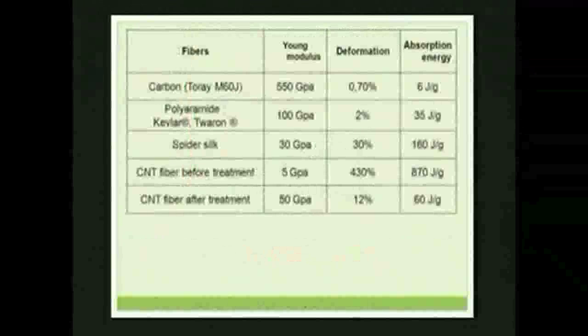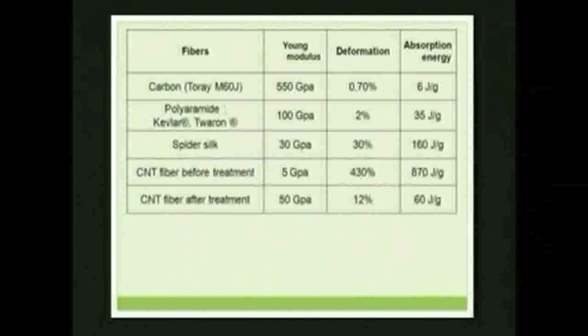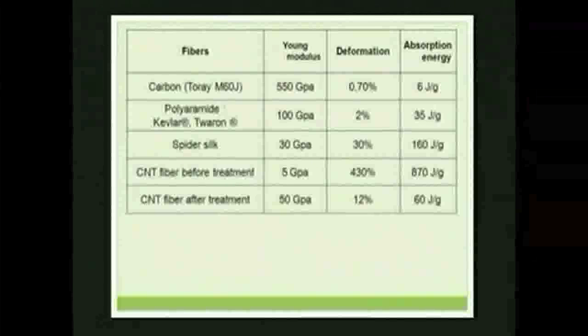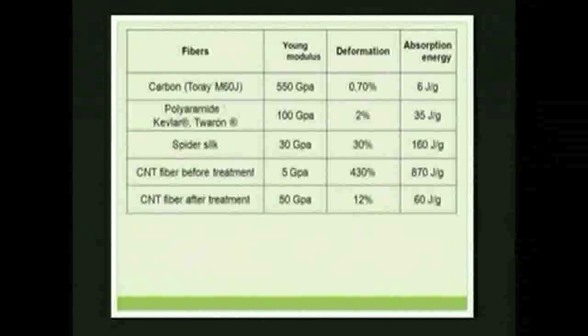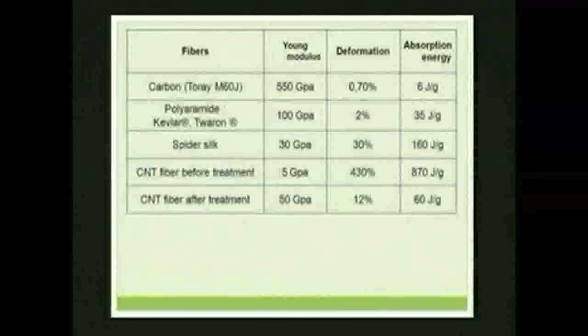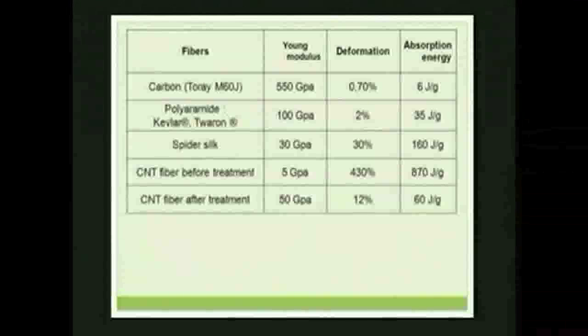Okay. Just to compare with other types of fibers, you see that we have very high energy absorption. This is the raw carbon nanotube fiber before treatment, the same after treatment. So, of course, here it's smaller than spider silk, but it's still higher than Kevlar. So, I think it's very interesting. Just to see carbon fiber. The best carbon fiber made by Toray has a very high Young modulus, but very low deformation rates. This is the reason why they are not flexible. They are very brittle. And the energy absorption is also very small. So, they are not suitable for protection applications. For some other applications, yes, but not these ones.